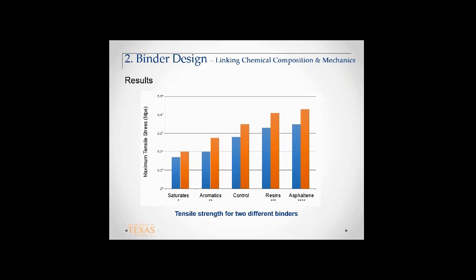This is just to show repeatability of the test. But these are the results. The blue is one binder and its derivatives. The red or orange is the other binder and its derivatives. So you have the control here. We know that stiffness decreases as you add less polar material and increases as you add more polar material. But this has to do with strength. If you look at the strength, it's the same thing happening. With less polar material, the strength decreases. You add more polar material, the strength increases. The change is different for different systems, but it's very consistent for both binders.